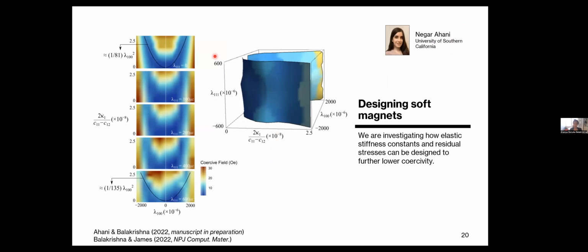What I'm doing together now with my student is looking at the interplay not just between the one magnetostriction and kappa 1 constants, but also the presence of other magnetostriction constants. Rather than having a quadratic relation, we are constructing a three-dimensional surface. If you have a soft magnetic alloy whose values are close enough to this surface, you can expect this new alloy composition to have a small hysteresis as well.